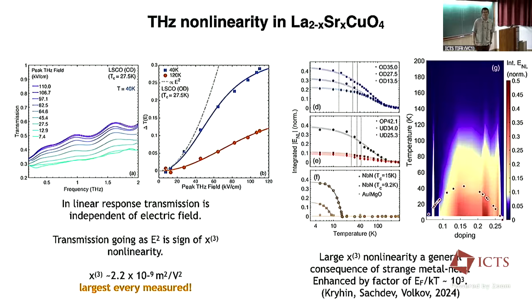Maybe I didn't get it properly. The common idea was that in the overdoped regime the correlation effect is much less, and the Fermi surface measured in the overdoped regime has very good agreement even with the band structure Fermi surface. So I'm a little confused when you say that in the overdoped regime you also really see this kind of nonlinearity. Where is it coming from? So this is an experimental result. That's a good question. Where does it come from?